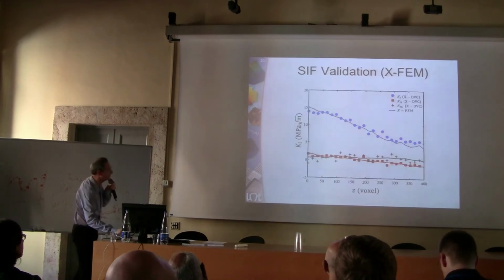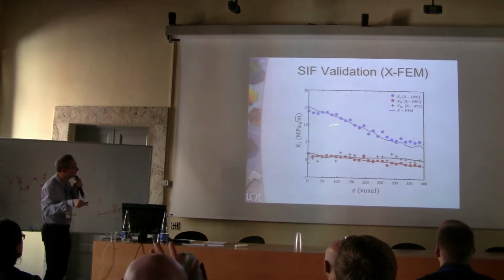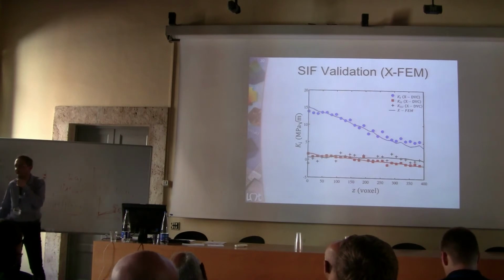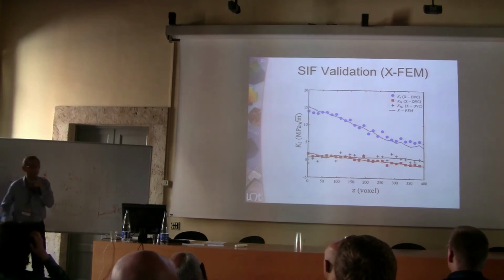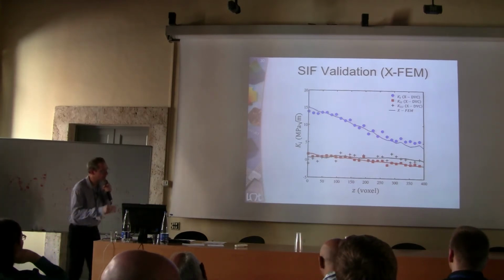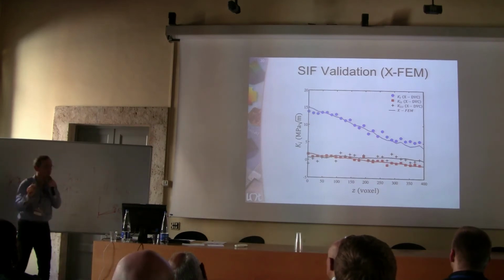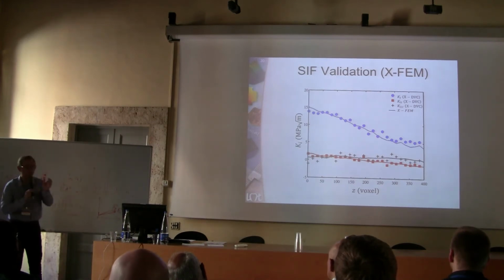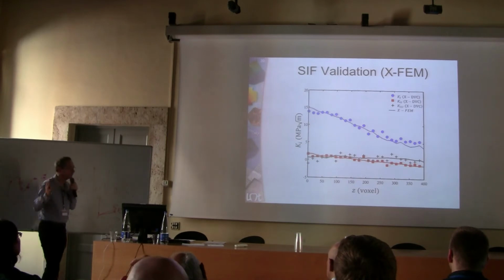...you would have predicted basically a constant stress intensity, mode 1 stress intensity profile, which is not the case in this particular experiment. This has to do with the scale of the samples and the fact that the geometry and the testing machine was very compliant.